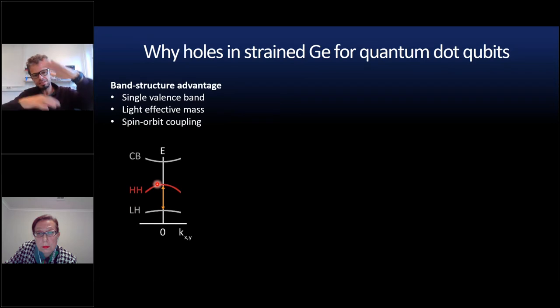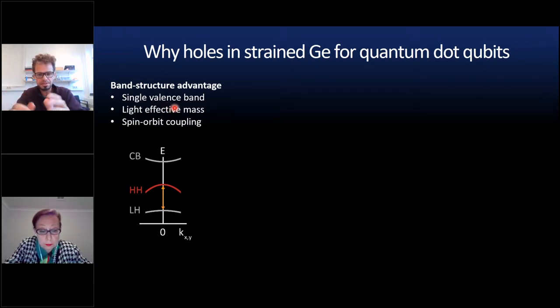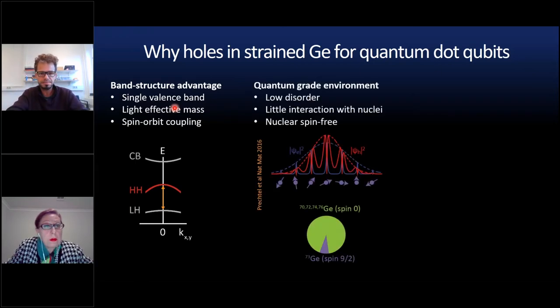So the energy spacings are very large, which is very important to keep quantum information where you store it. Holes in strained germanium have an extremely light effective mass. And this means that you can achieve quantum confinement with larger structures, because the energy level spacings are larger. And there is spin orbit coupling, which allows you to drive qubits locally via electric fields that then translate to magnetic fields.